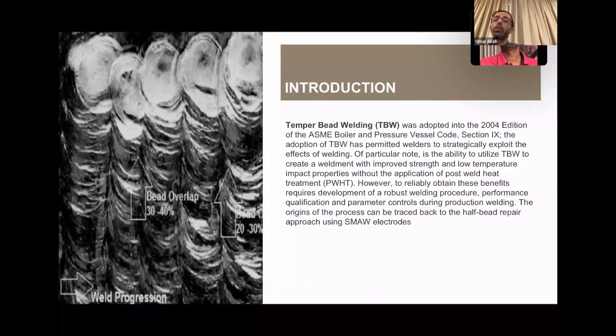So as an introduction, the intent of temper bead is to control the mechanical properties of a weld joint and a heat affected zone without the need for heat treatment. So it provides the same mechanical properties as the heat treatment. This technique was adopted in 2004 in ASME Section IX, but that doesn't mean it was not in use long before this date. We have a record of using temper bead welding since the 1980s, especially in nuclear plants where accessibility is a concern. The first technique used in the 1980s was the half bead repair using SMAW electrode.